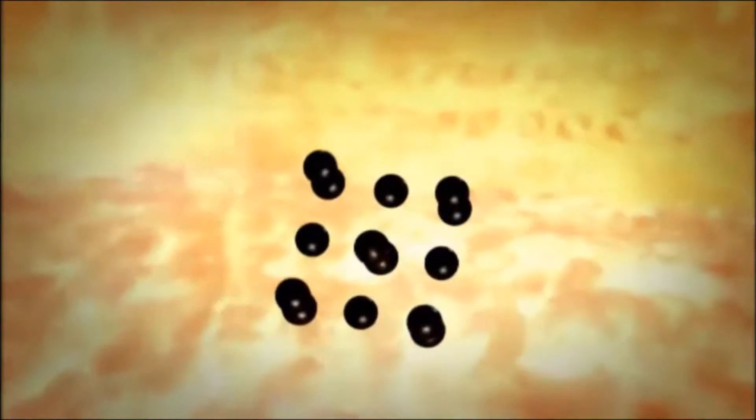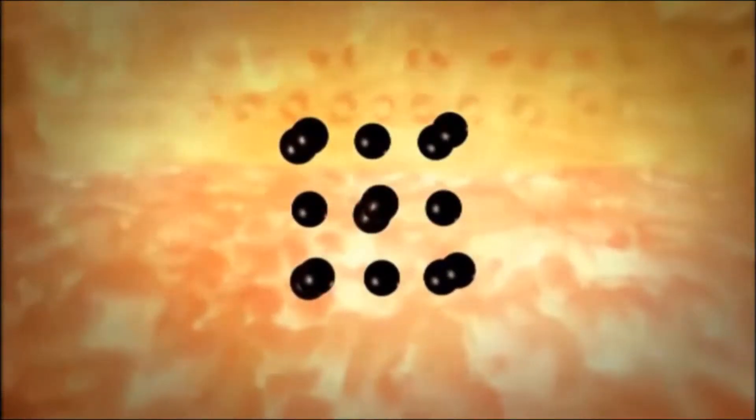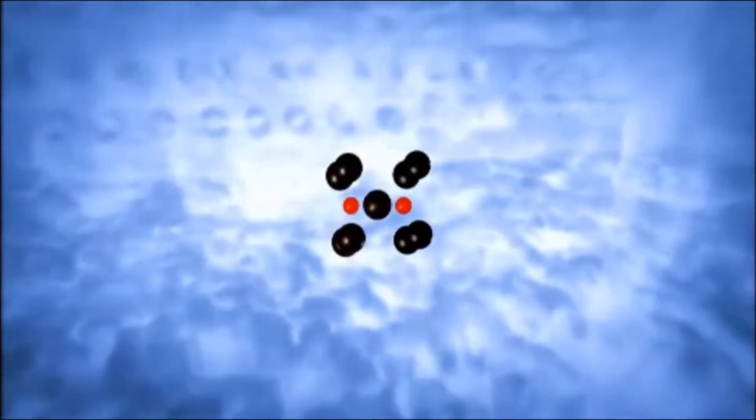There is actually more space between the iron atoms at high temperature. But when this high temperature form cools quickly, it contracts, and the carbon atoms become trapped in between the iron atoms. If it does that, the iron can't fully assume the structure that it would like to. It will be distorted by virtue of the fact that the carbon atoms are lodged into spaces that are really too small for them to fit into. And that kind of form of steel — iron and carbon mixed together — is very, very hard, very, very strong.